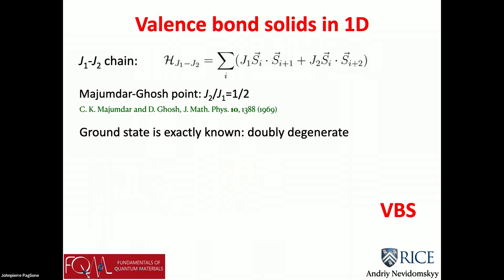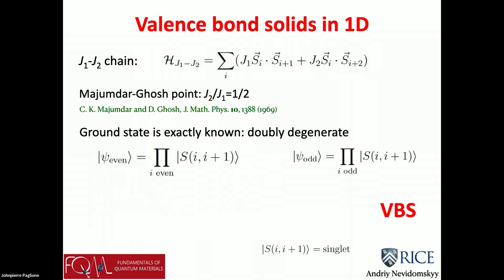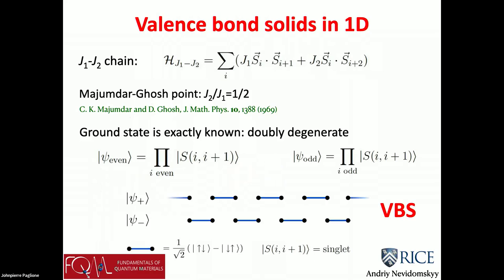The simple example is in one dimension. If you take a Hamiltonian which is a chain and only has nearest neighbor and next nearest neighbor interactions, it turns out that there is a special point, when the ratio of the two coefficients is 1/2, where the ground state becomes one of these two things. There are exactly two, not infinitely many, but two global ground states. And they essentially come from how you cover the one dimensional line by dimers in an alternating fashion. Why alternating? Because any one spin can only participate in one dimer. And once it's occupied, that's it. The next one has to find a partner, either the one to the right or the one to the left. And there are two ways of doing that.